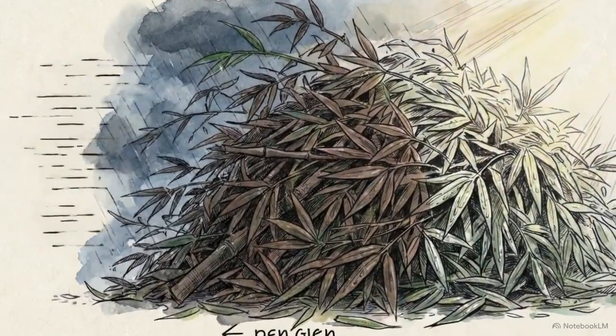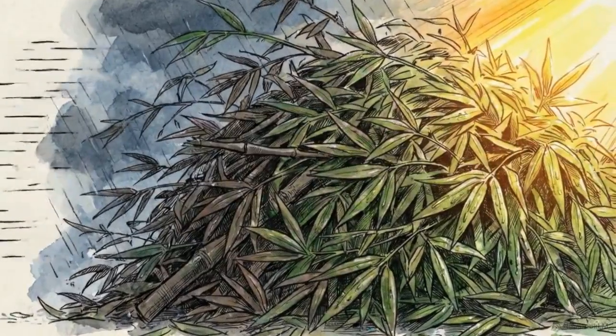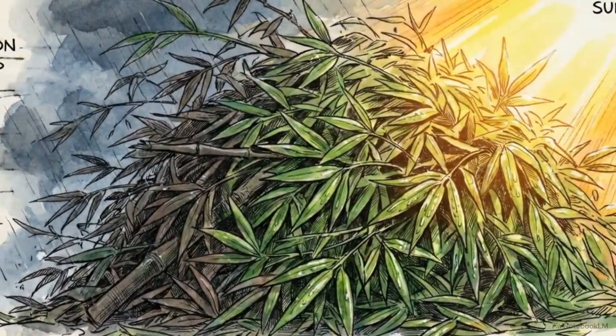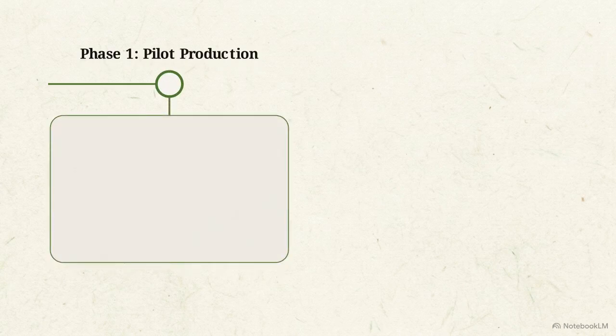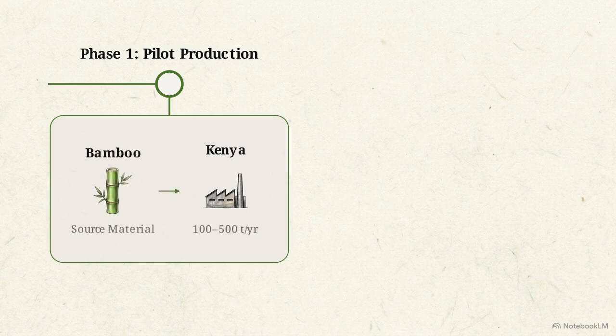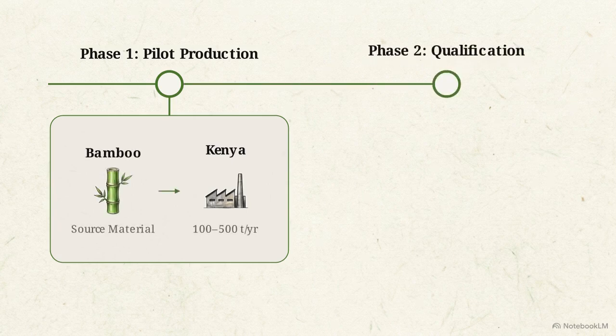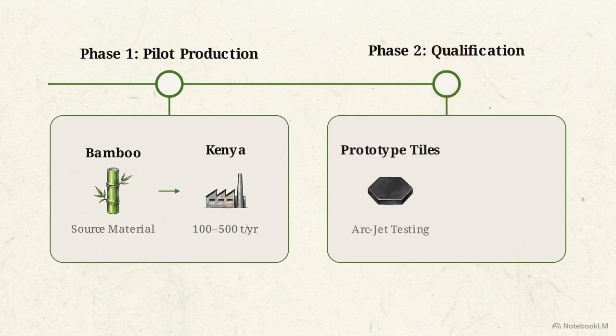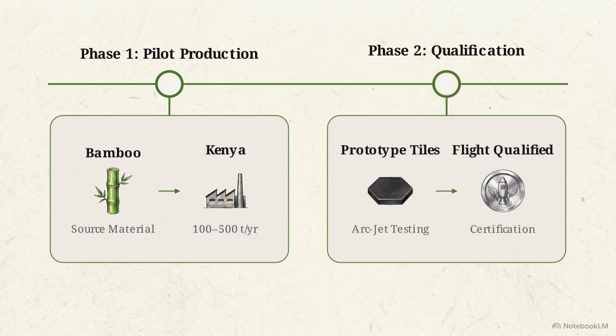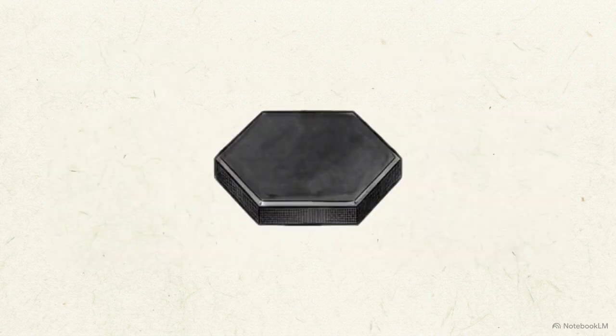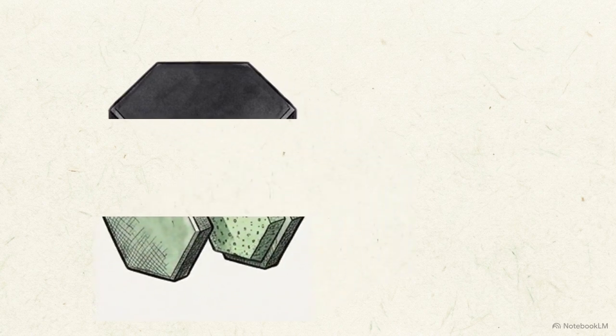To de-risk this transition, the strategy starts with Phase 1. This involves commissioning a specialized pilot extraction plant in Kenya, producing 100 to 500 tons annually. Once proven, Phase 2 provides this material to contractors for prototype tile manufacturing and rigorous arc-jet thermal cycling tests. Early engineering adoption might avoid full replacement entirely, instead utilizing hybrid tiles that place a highly insulative biogenic core underneath a traditional mineral outer coating.